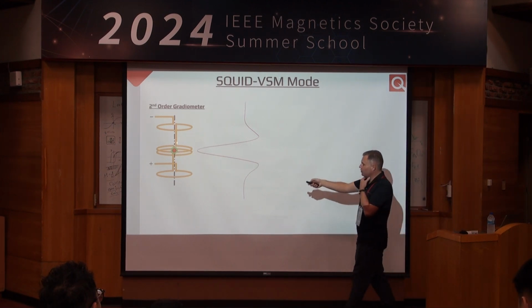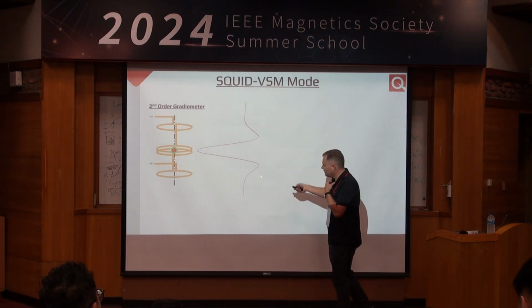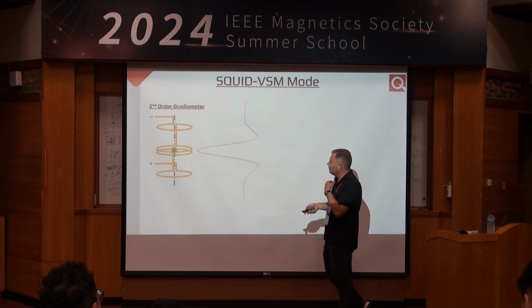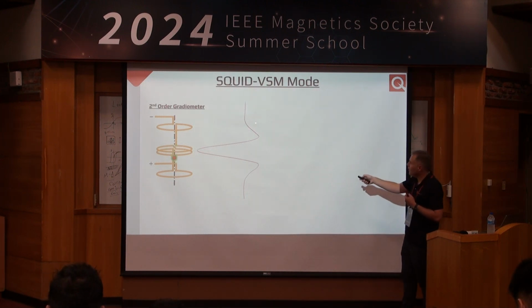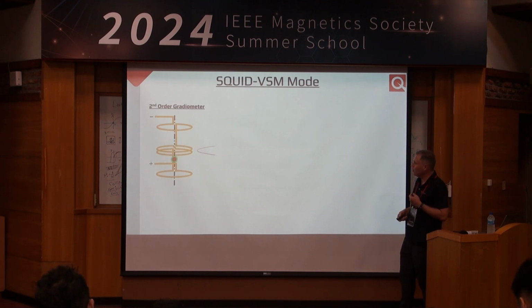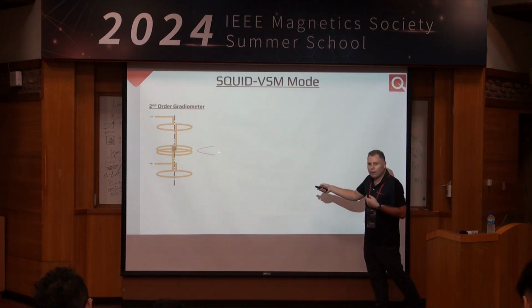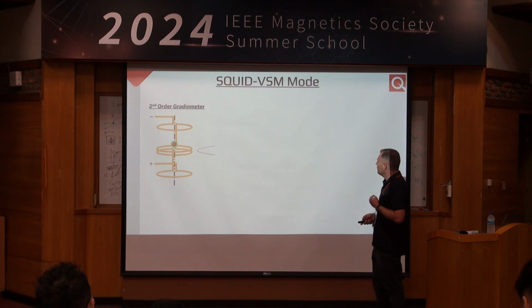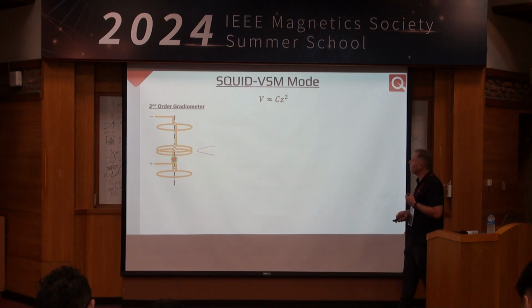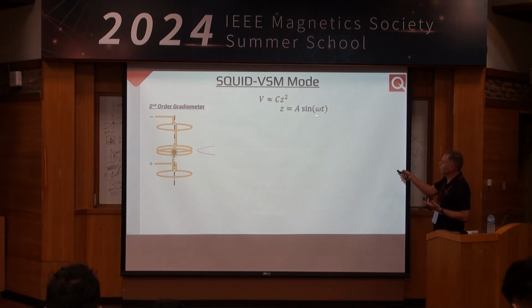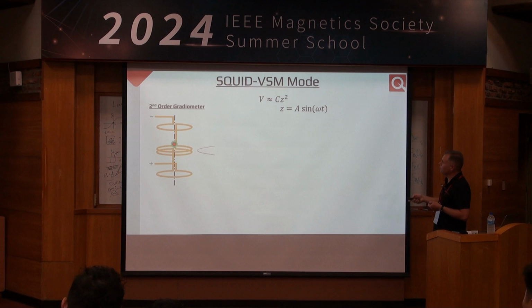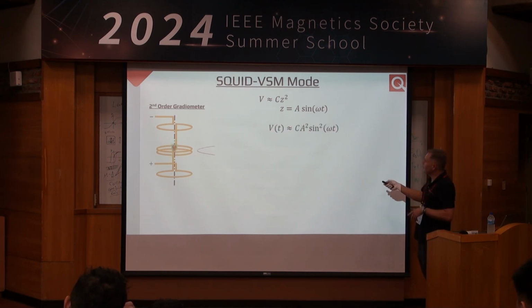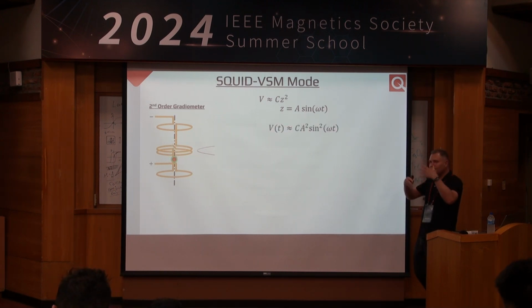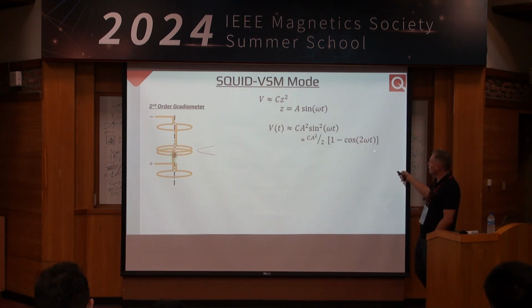So it's the same detection circuit, same second-order gradiometer, same voltage waveform. Here's our sample. But instead of moving the sample through the gradiometer, we're just going to jiggle it. Okay? So we don't have to worry about most of this waveform. We can throw that away. And all we have to deal with is this little parabolic section right here. Follow the bouncing ball. So again, we've got a parabolic voltage response here. We know how the sample position is a function of time and frequency and with a given amplitude. Go through here, plug this in, use one of those trigonometric identities in the cover of the book, and we can get this type of voltage here.